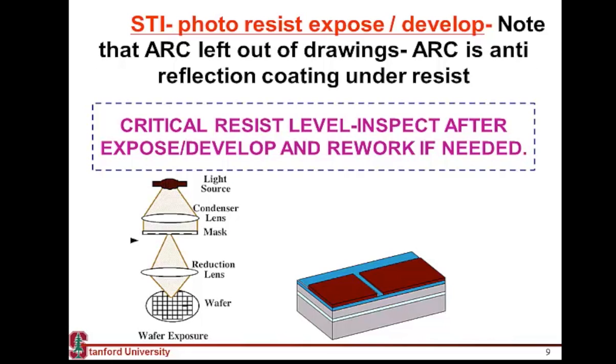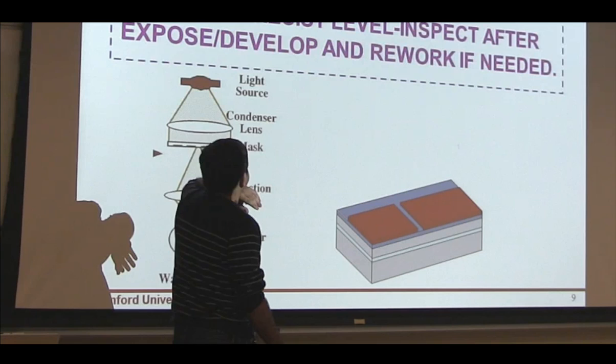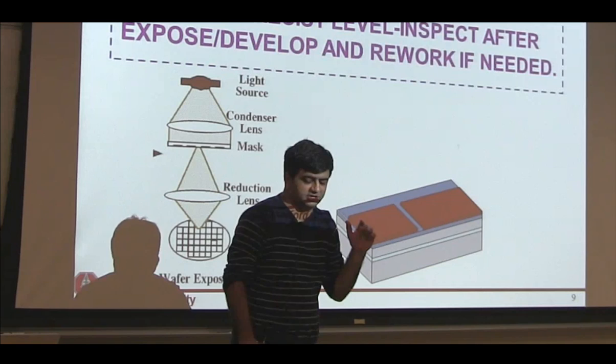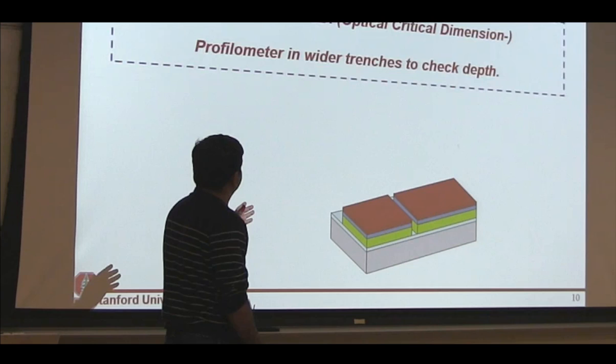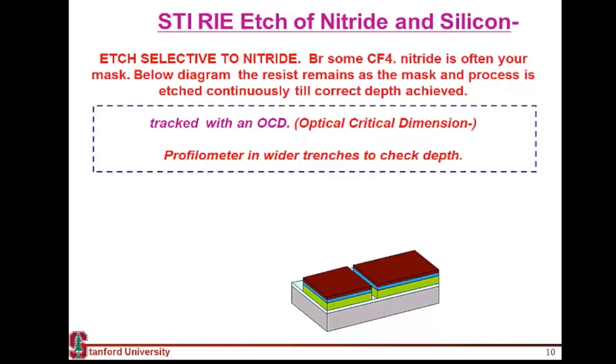which either form bonds or break bonds depending upon if you expose them with a high-energy light. And if you have worked in a fab, you might have seen these equipment where you spray a photoresist and spin the wafer. And the thickness of the photoresist primarily depends upon how fast you spin your wafer. So the next step which is done is lithography. That is, you expose this to light and you make these patterns. Many times when you do in SNF, you don't use this thing called anti-reflection coating, but most of the time if you do it in an industrial lab, below your photoresist, you use anti-reflective coating because when you shine light, you'll have reflecting back from the surface too. And you avoid forming standing waves in your resist. So you use anti-reflective coating.